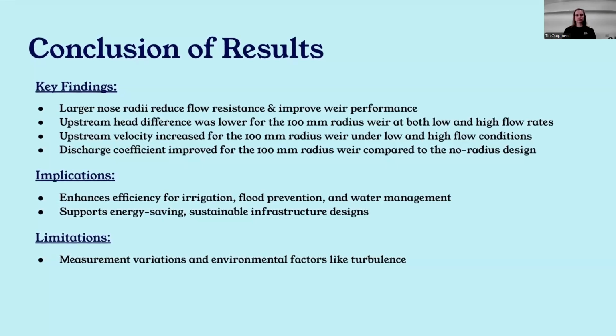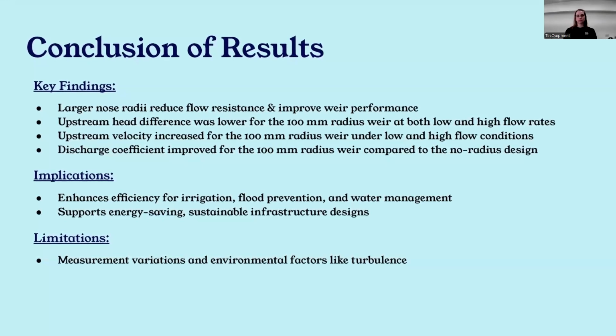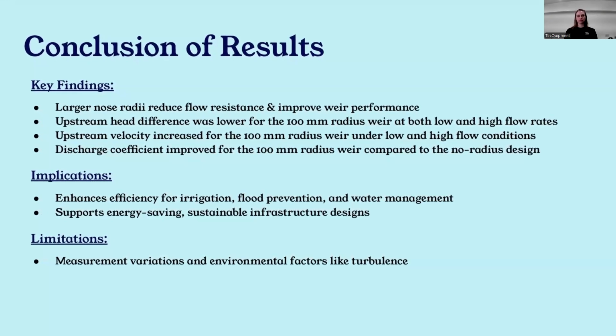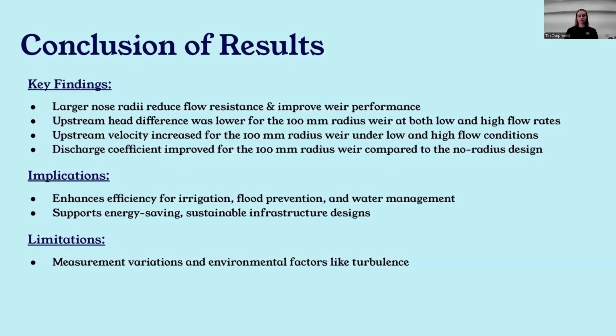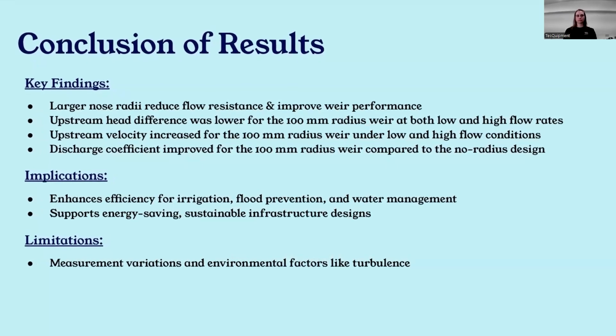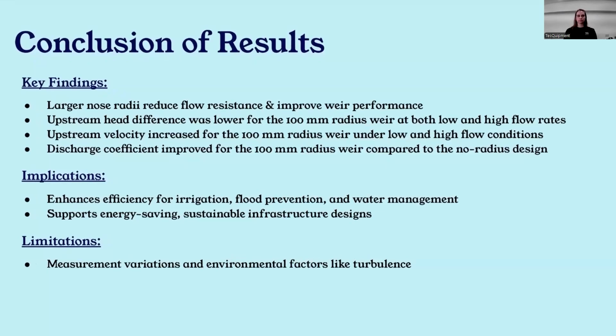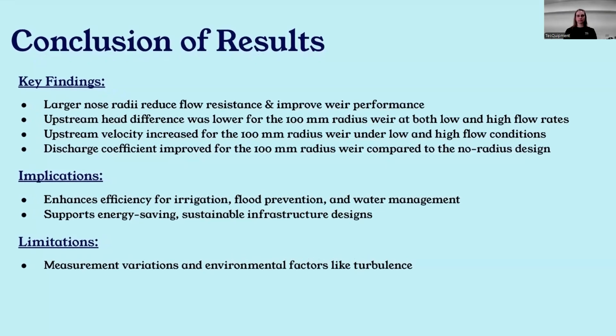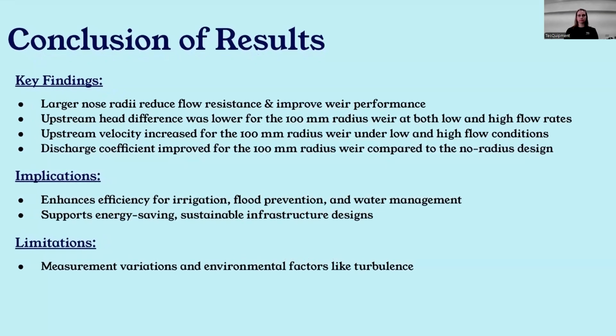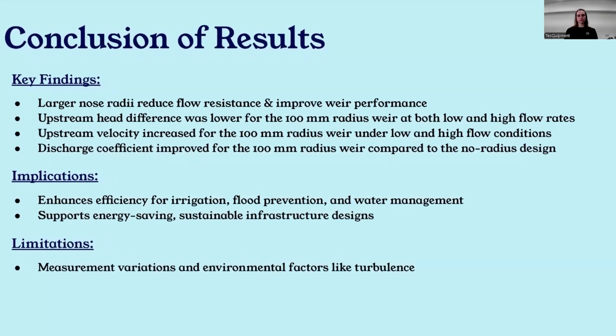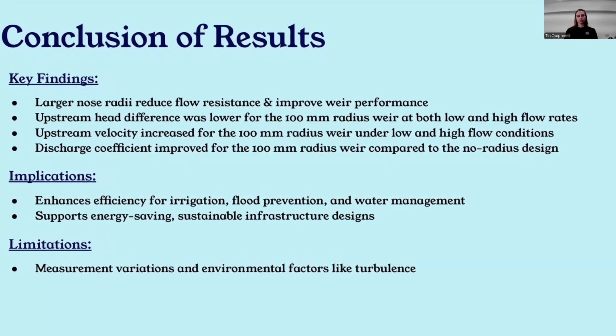At low and high flow rates, the no radius weir had a 4.9% and 6.08% higher upstream head difference than the 100 mm radius weir. Upstream velocity for the 100 mm radius weir was 16.4% and 16.1% greater at low and high flows respectively. The discharge coefficient using total head was 8.61% higher for the 100 mm radius weir, aligning with expectations.